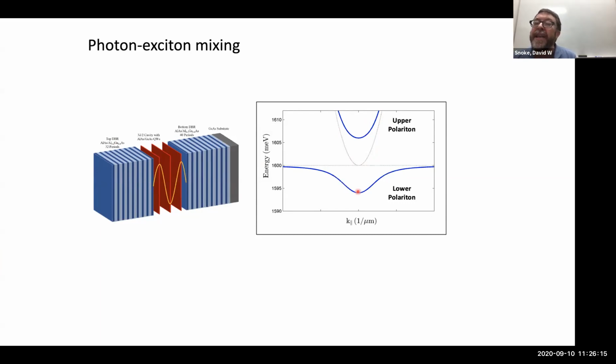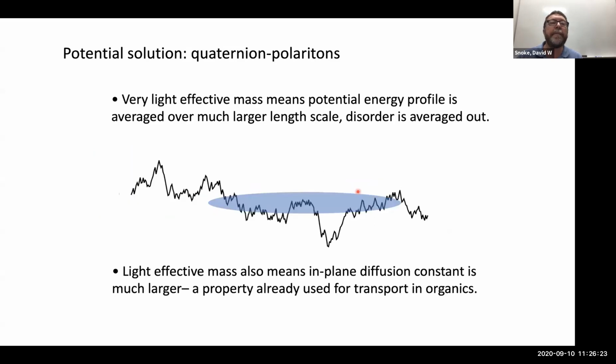Many nice things happen. You get line narrowing, you get a light effective mass, you get averaging over disorder. Just in a hand-waving way, in general, the effective mass of the polariton is given by the cavity mass of the photon, not by the exciton mass. And so these masses are 3 or 4 orders of magnitude lighter than an exciton. That means they're delocalized over a much wider range, and so they're averaging over that disorder. And so you see very sharp lines for the polaritons that you would not see for the excitons in that same structure.